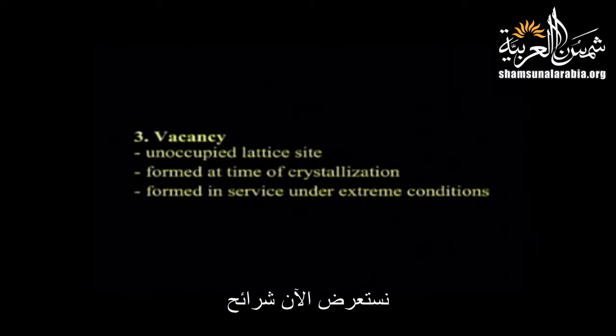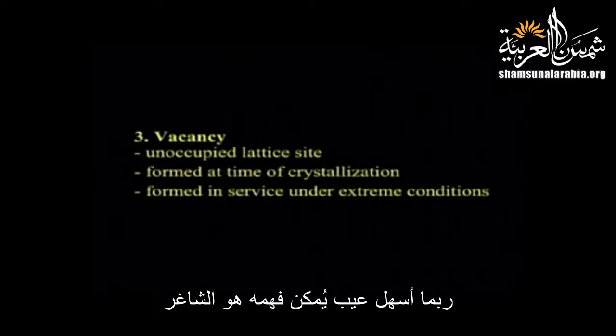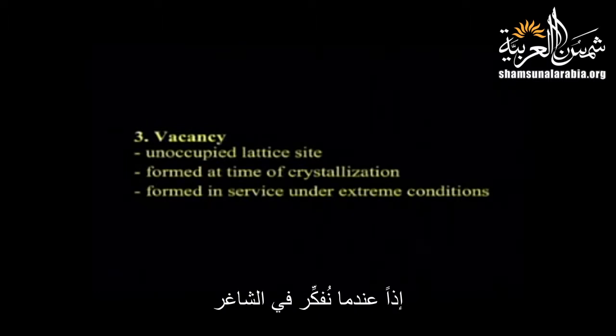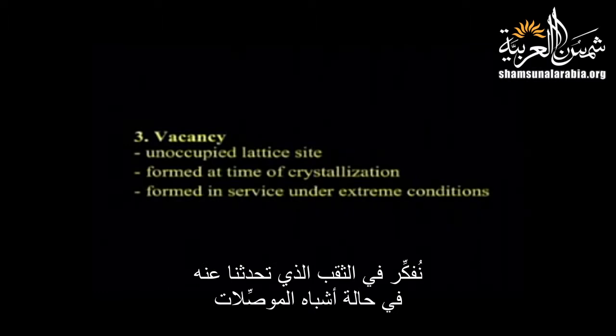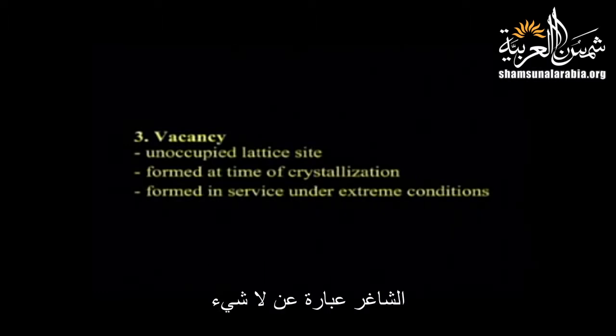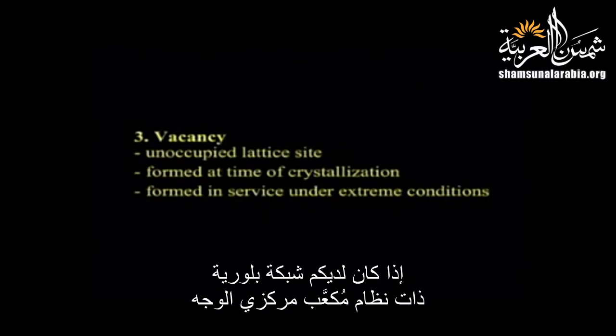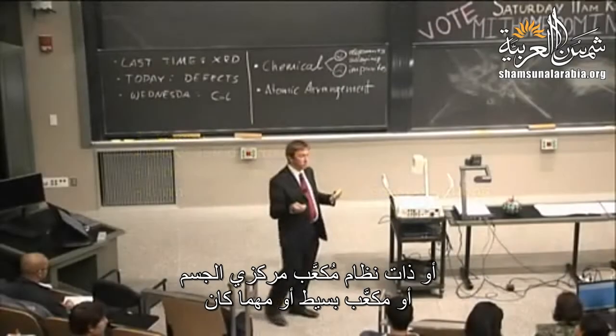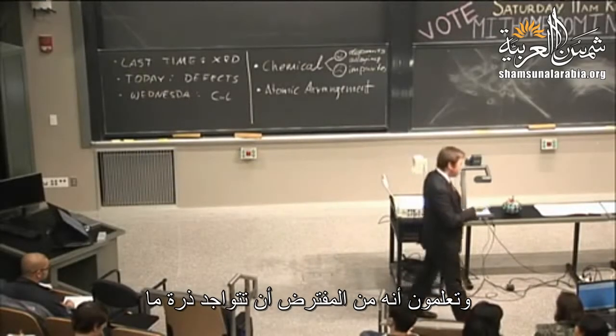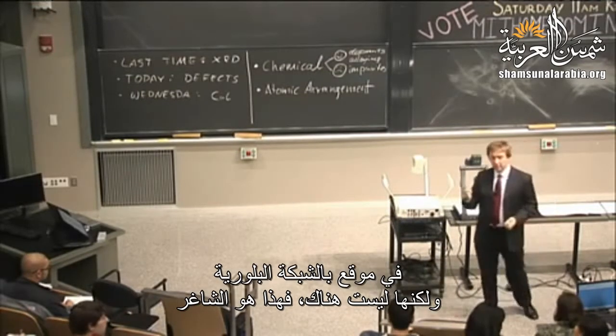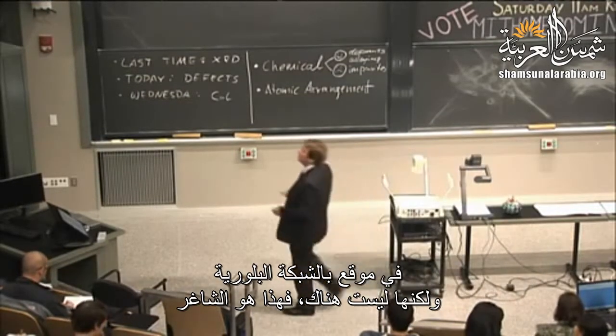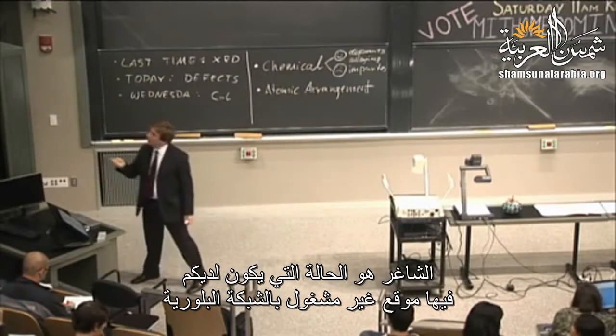It's one of the challenges in that whole undertaking. Okay, so we're going fairly at a clip here through this taxonomy of point defects. In the taxonomy of point defects, perhaps the easiest defect to understand is the vacancy. So when you think of the vacancy, think of the hole that we talked about in the case of semiconductors. Vacancy is nothing. It's a missing atom. So if you have a crystalline lattice and it's FCC or it's BCC or it's simple cubic, whatever you like, and you know that there's supposed to be an atom at a certain lattice site and it's not there, that's a vacancy. That's a situation where you have an unoccupied lattice site.